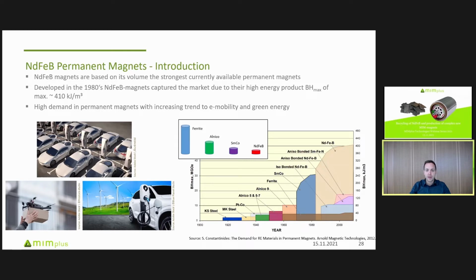Permanent magnetic materials have been developed over the last 100 years, with a lot of different alloys. But neodymium iron boron has the strongest energy product of all developed materials so far, even though the alloy is only roughly 40 years old. If you compare the size of a magnet, a neodymium iron boron magnet is only 1/10 of the size of a ferrite magnet and roughly 1/5 of alnico, and also much smaller than samarium cobalt, which is also quite a commonly used permanent magnet alloy.